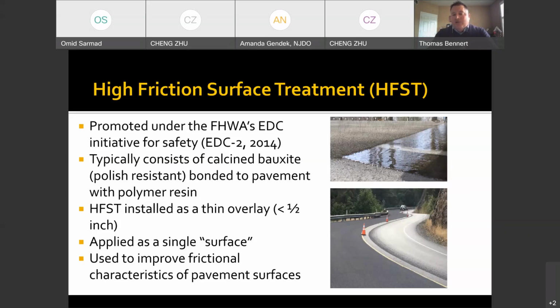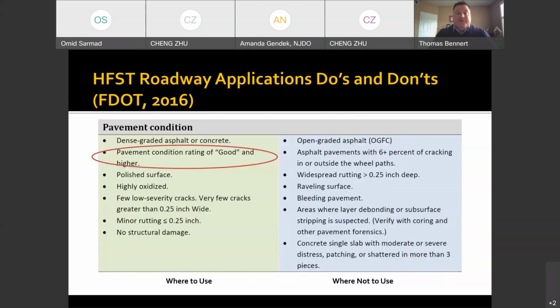We use a typical epoxy that's applied to the pavement surface. And then you can see in the upper right picture, the aggregates are placed over top. They're dropped down onto the epoxy and allowed to essentially seat themselves into that epoxy and are glued in. The thickness of this material is relatively thin. You're talking less than 1/2 of an inch application. We generally like to see them around horizontal curves where we generally have some lane departure issues. But in most cases, what we generally see the municipalities and the state using are in declines where there's braking and the horizontal curves. They do significantly improve the friction over what we would generally have as a typical pavement surface.